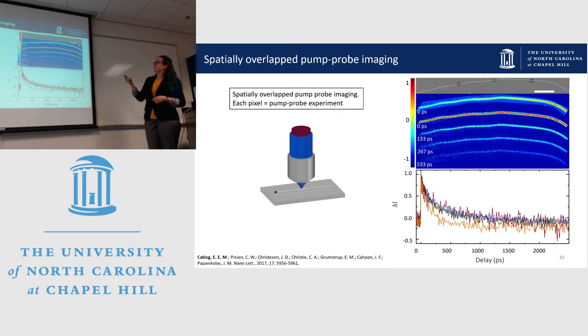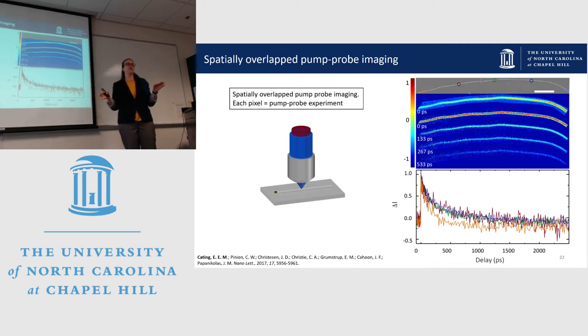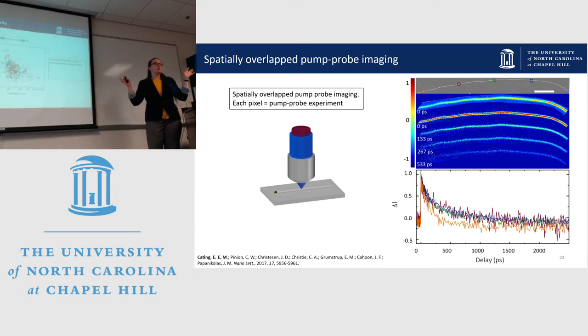To confirm this, I took transients at each of 5 locations along this wire, and they're here. And you can see that the first 4, so from here to here, do overlay very nicely. The last one is a little bit faster, right? But still, this difference is not nearly enough to give us the 2 orders of magnitude variation in the surface recombination velocity that we saw. But again, that's still just one wire.